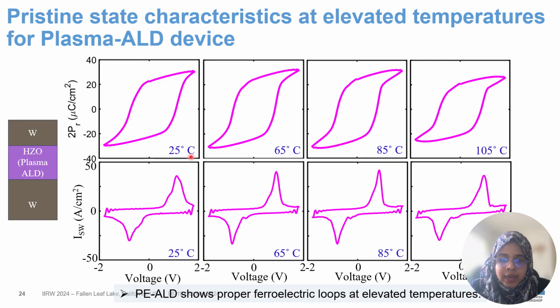What we are seeing here is that starting from 25 to 105 degrees Celsius, we don't see any significant pinching in our hysteresis loops, and also we don't see any double peak in our switching current as well. What does it tell us?